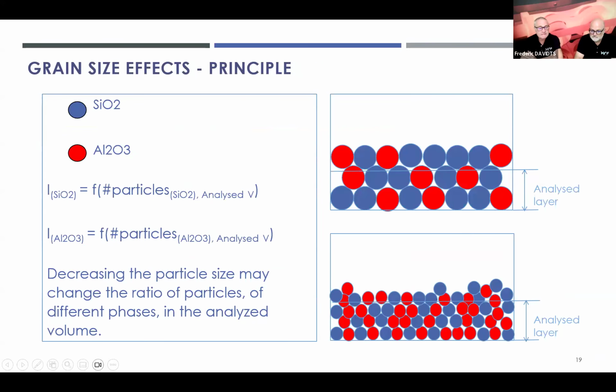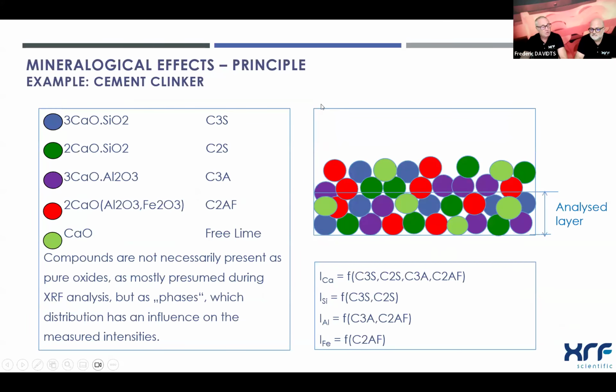I'll pick out just two of the effects that take place, just to explain how we can resolve them. In this example, we assume that we have two particles, silicon oxide and aluminum oxide. The grain size is very important, because if you have, for example, a larger grain size, we have a certain distribution of those two particles, and the intensity of the particles is really a function of the number of particles within those analyzed volumes. Now, if I start grinding the samples to a smaller grain size, the distribution may be different, and therefore also the intensities may be different. Although we have the same concentration in both samples, grinding the sample down to a smaller particle size may drastically influence the measured intensities. The second effect is the mineralogical effect.